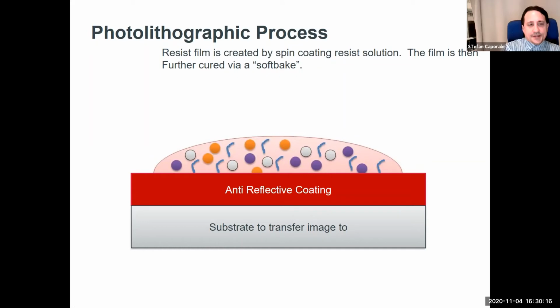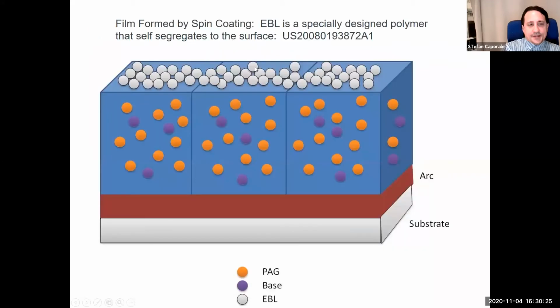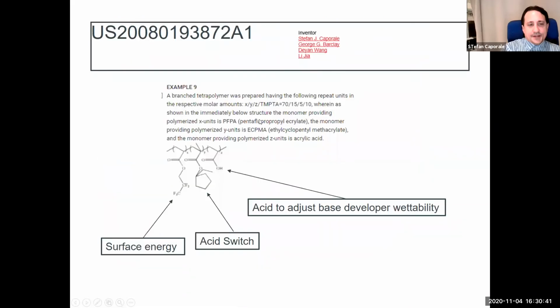And then you soft bake that normally at 60 to 80 degrees Celsius to remove the residual solvent and get your film. So now your film is set up. The embedded barrier layer is specifically designed to come to the surface, and then your PAG and base are evenly distributed throughout the film. This is actually one of my other patents. Again, I hold 19 patents.